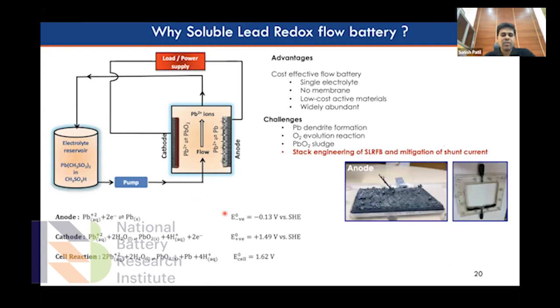I talk about the soluble redox flow battery. In this area, we make use of lead methane sulfonate as an electrolyte. What we have is no membrane. This is rather a simple battery. The beauty of this battery is there is no membrane, and we dissolve the electrolyte in this reservoir. We use a single electrolyte, no membrane, low cost active materials, and widely abundant. Initially we had a lot of challenges to address: lead dendrite formation, oxygen evolution, and lead oxide sludge. We addressed all these questions, and perhaps I can go to my last slide.